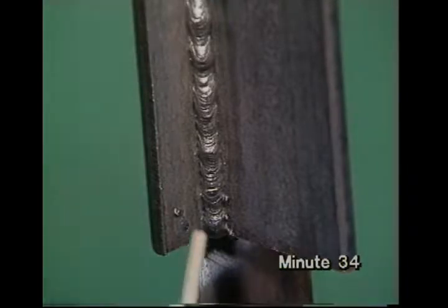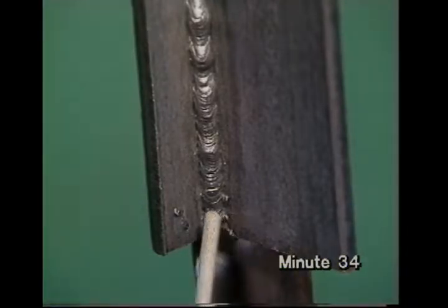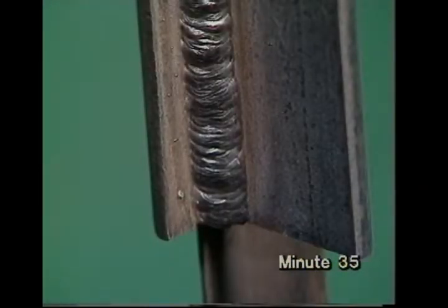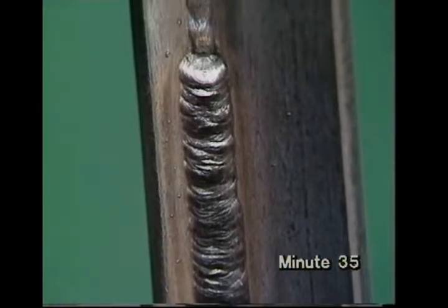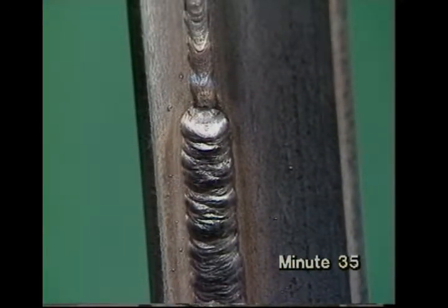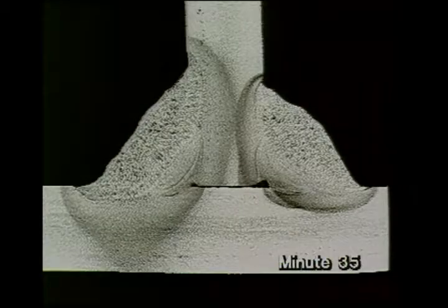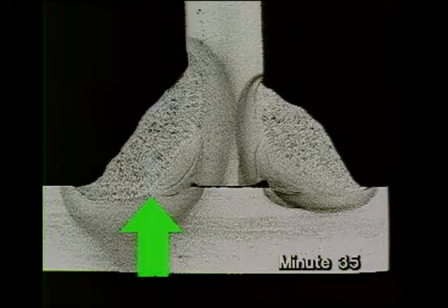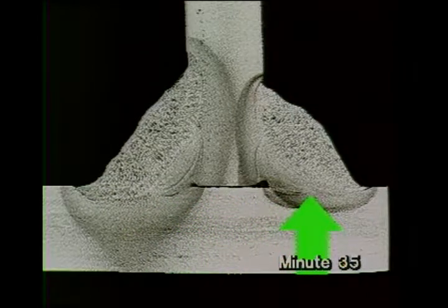If you need a larger weld, build it up by weaving, which is much easier than adding extra straight beads when welding vertically. Pause at each side to leave a flattish surface. This macro section compares a weld made flat on the bench with a straight profile and one made vertically, where it's more difficult to control.